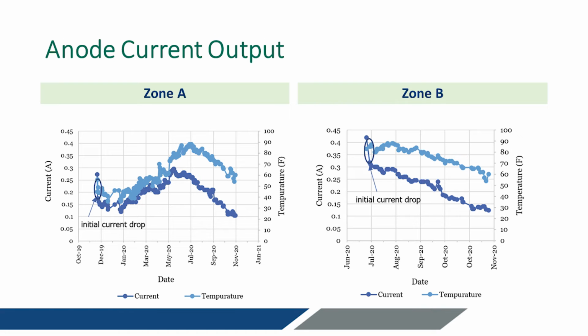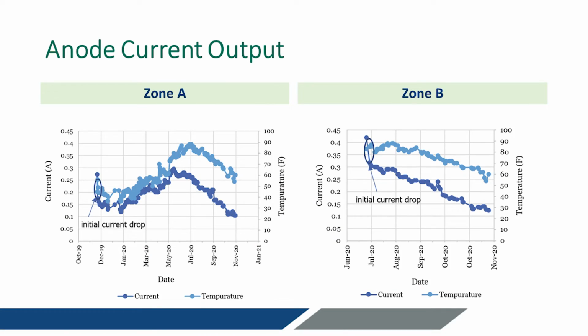And then you can see anode current, so effectively the anodes are pumping out current over time. And so this is anode current over time, but it's really highly related to temperature because that's resistance. So you can see as the temperature goes up, current goes up. As temperature goes down, current goes down. So as it gets colder, the risk for corrosion is lower. As it gets hotter, the risk for corrosion is higher. So the anodes work really with the temperature to combat the corrosion.